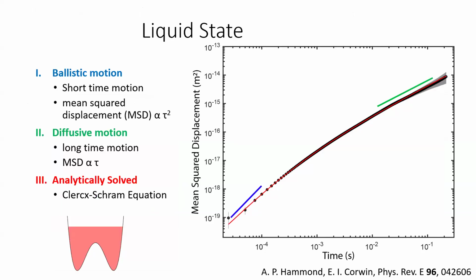And then what we can do is look at the motion of this single colloid when the system is in the liquid state. So I shake it up, I put it down, I wait a few minutes, and I can look at it for times between about 10 to the minus 5 seconds up to close to a second. And I can measure its mean squared displacement. And amazingly, I can actually measure the crossover from ballistic to diffusive motion.